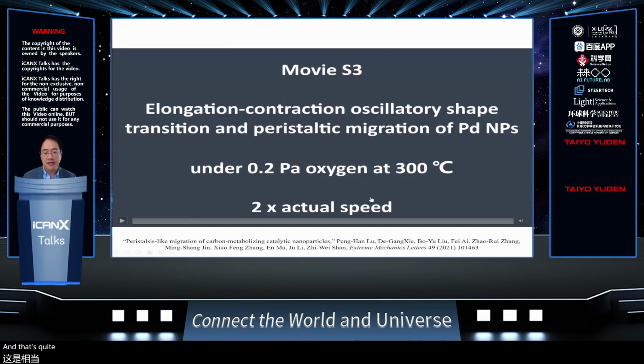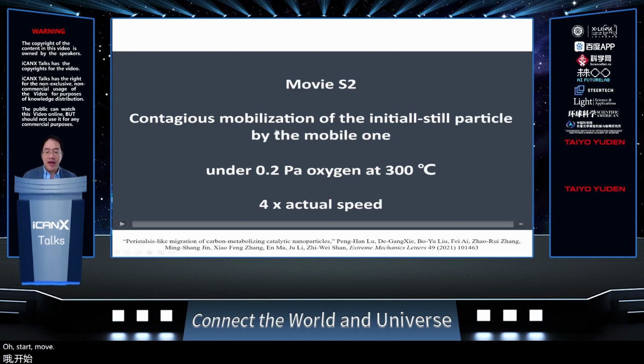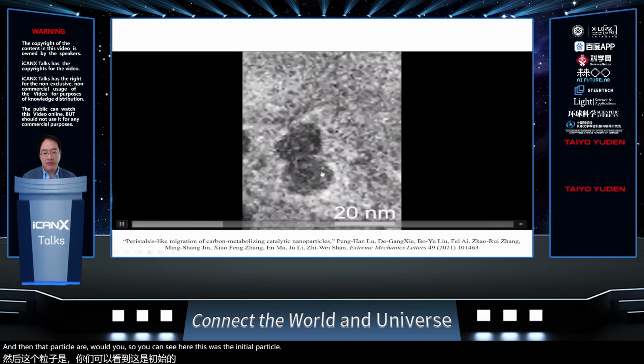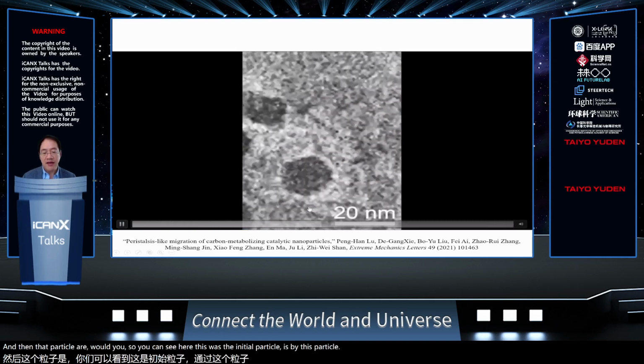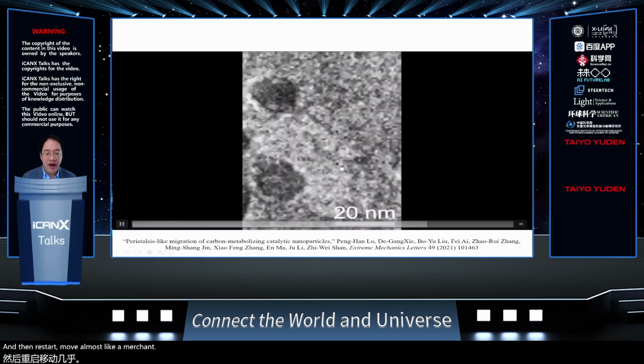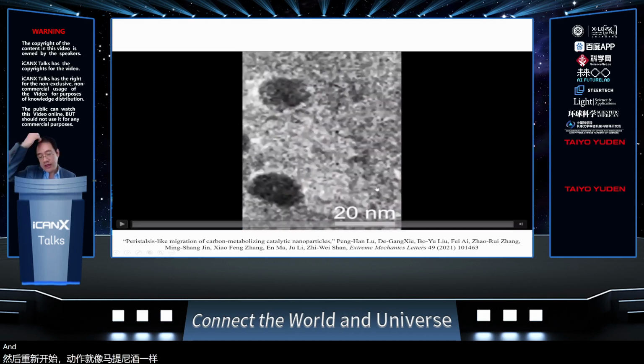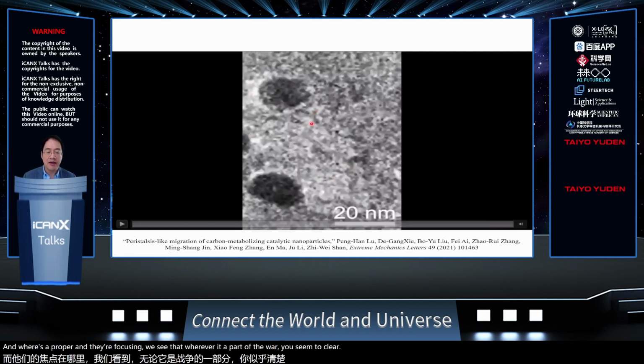And that's quite surprising. In fact, they move like zombies. Initially only one starts to move, and it actually has to sort of bite another particle which was stationary, and then that particle would move. So you can see here, this was the initial particle, it bites this particle, and then it starts to move, almost like in a chain reaction. And with proper under-focusing, we see that wherever the particle moves, it seems to clear some track. And that was actually surfactant that was used to disperse nanoparticles on this TEM grid.